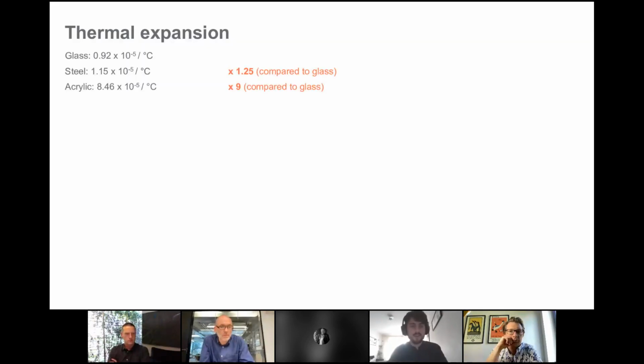Another really interesting thing about acrylic is its thermal expansion. All materials have a degree of thermal expansion, basically growing when hot and shrinking when cold. Here I've got some numbers for comparison: glass, steel, and acrylic. Steel expands about 1.25 times more than glass, and acrylic is 9 times more than glass. You'll see 9 times more expansion and contraction for a given temperature change compared to glass. That's significant. That's a lot, and I'll talk about how that manifests itself in the design.